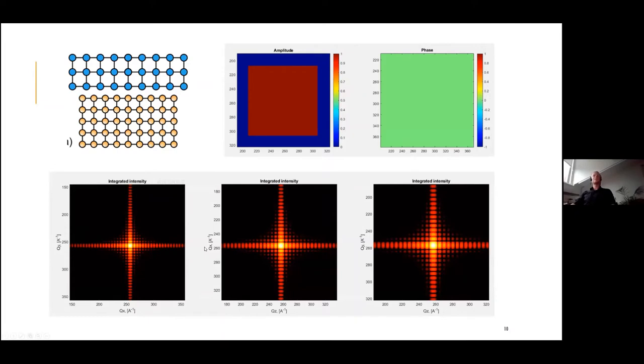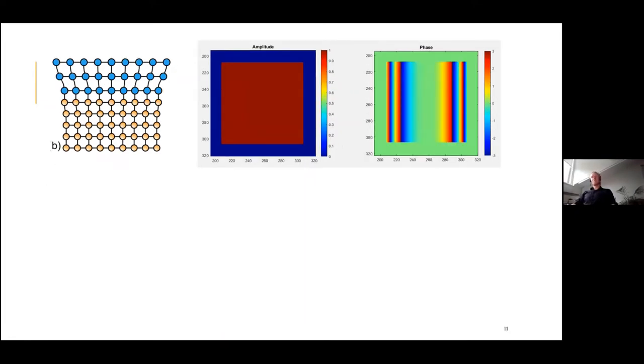So this is the intensity. However, if you focus on some elastic strain, for example, in semiconductor materials, when you have a mismatch between two structures which are close together, there is a misfit strain that appears at the interface of these two structures, trying to accommodate the lattice constants of each of them. And you get profiles, something like that. So the phase has certain curvature, which is not linear.